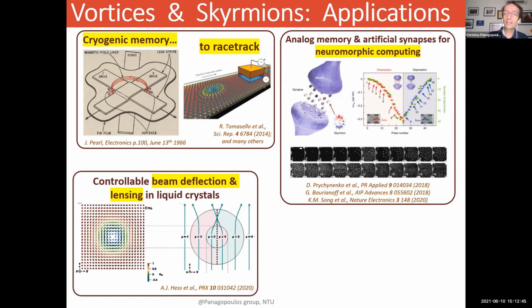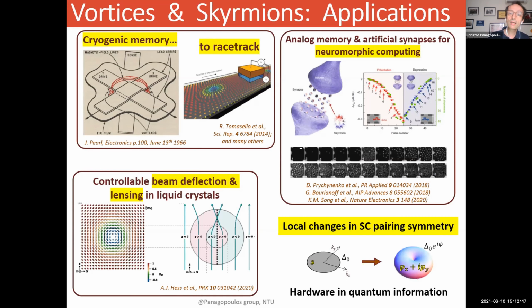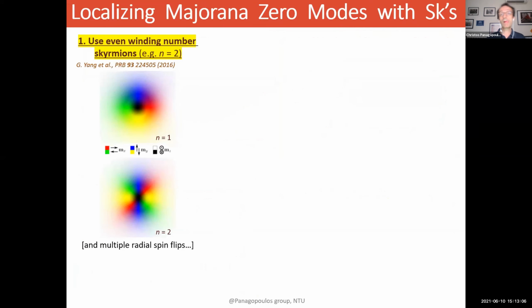What we find particularly exciting, and I would like to say a few words about it today, is that one may actually use these magnetic skyrmions or these magnetic textures to induce local changes in the superconducting pairing symmetry. And this is especially useful and important because one can use this possibility for hardware in quantum information. Now, why would this be? Because the possibility of having localized Majorana zero modes with skyrmions has already been discussed, and it has been a subject of intense investigation for the past 5 to 10 years.